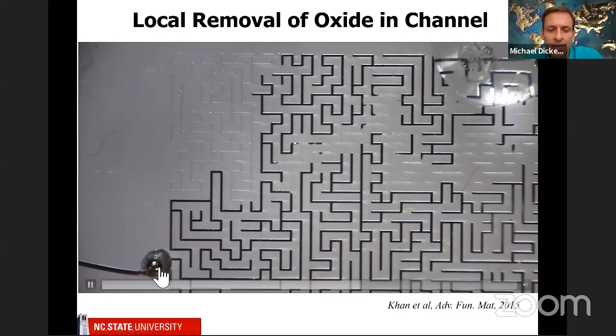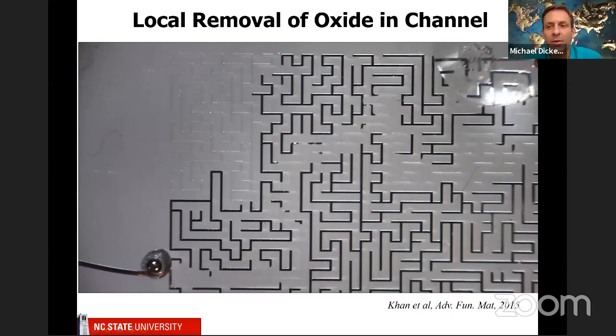We apply a voltage and that removes the oxide from this leading edge. And when you remove the oxide, remember it wants to form a sphere. And so it spontaneously withdraws and forms this spherical shape. And by the way, it solves the maze, which is kind of cool. So the electrical path in this maze is the solution. And so it's basically just following the electrical path. Now this looks really neat and cute, but the real challenge is, the physics here are a little bit obvious, and that is it just wants to bead up to minimize its surface energy. How do you get it to go back in?